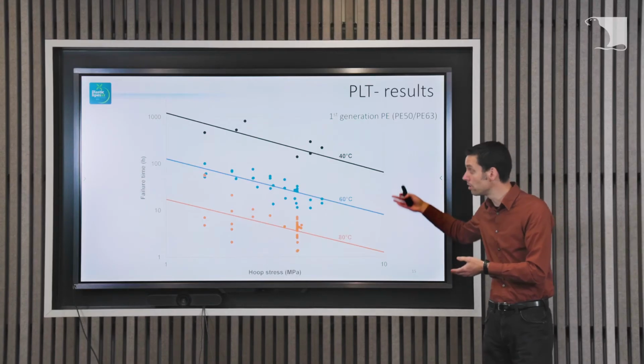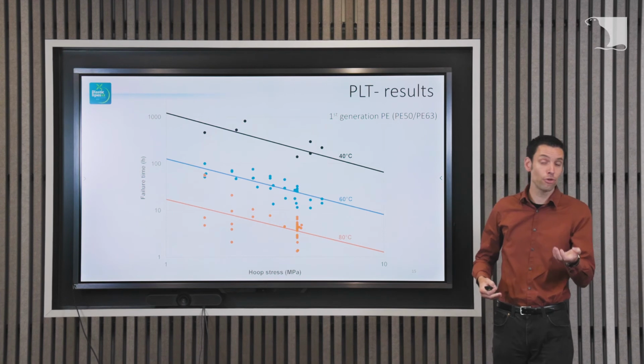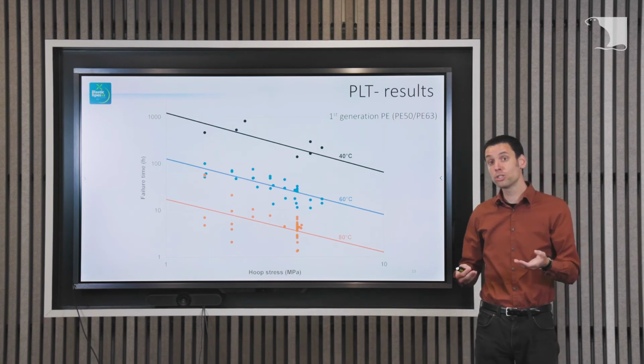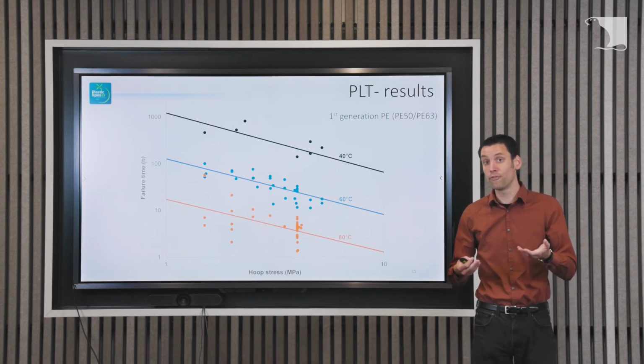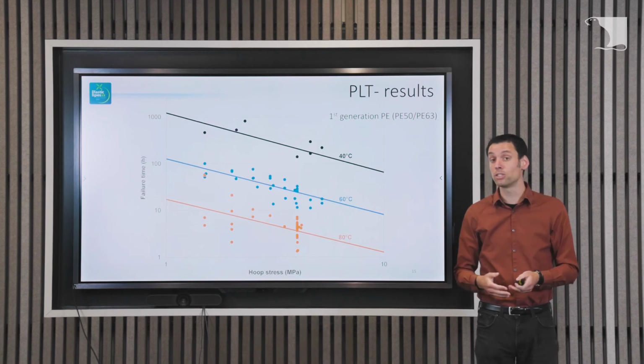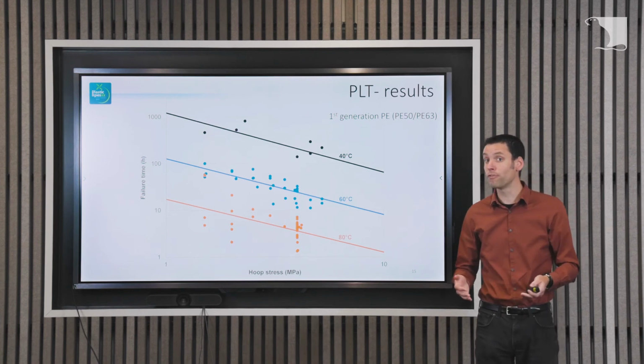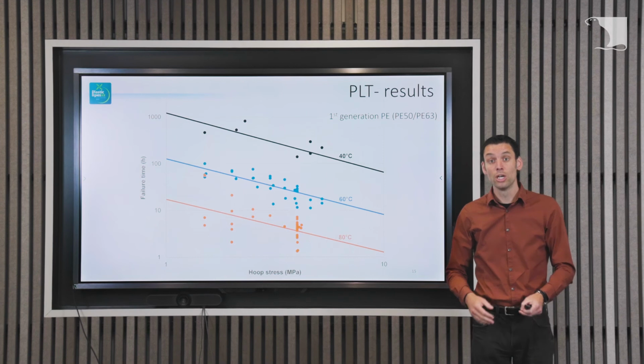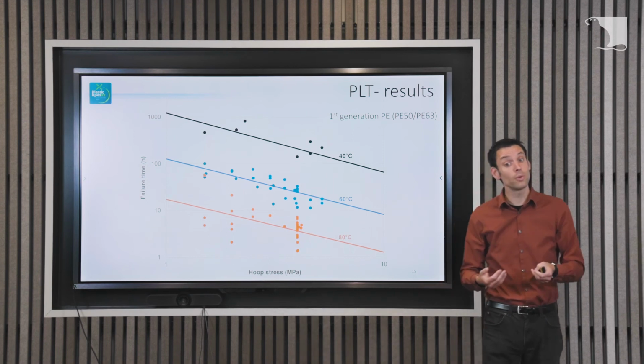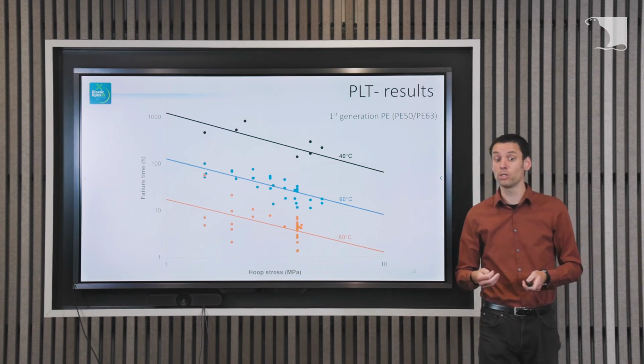And then we can see, okay, what time would it take for the first generation to fail due to point loads? And that was actually in good agreement with practice. Because if we extrapolate these results, we came at 35 years. And the first point load failures in the Netherlands were after about 35 years in use. So it really gave us confidence that we get a good result here with the point load test.